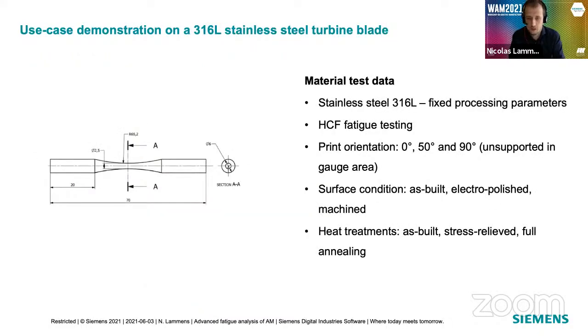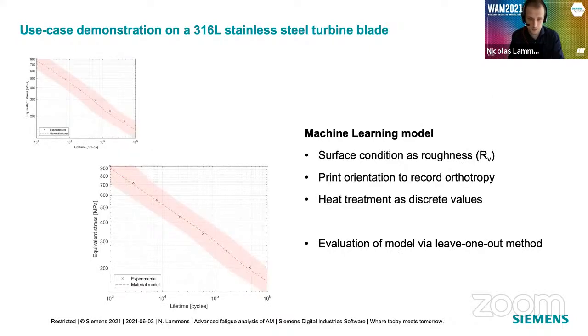And to illustrate briefly the results that we've achieved so far, I wanted to show you some results that we did on a steel turbine blade analysis. It was a 316L stainless steel that was used. And to build our fatigue material model, we started with simple coupon test data, high cycle fatigue test data. All of them were printed in 316L, but with a fixed set of processing parameters. The only things that we changed were print orientation, the surface condition, and the heat treatment that was applied. So that gave us a small set of test data that we could use to train our machine learning model.